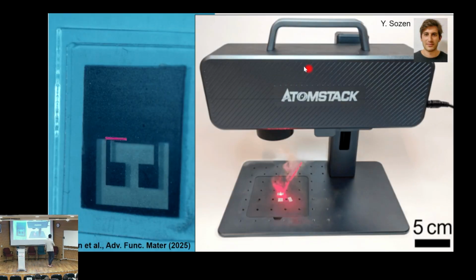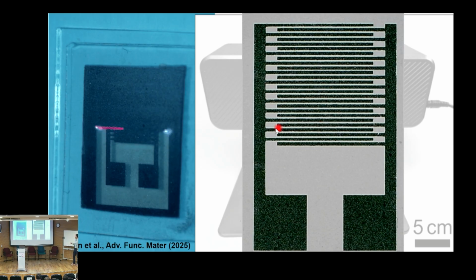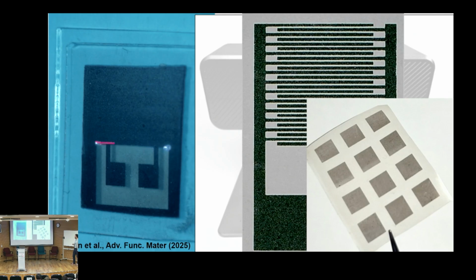When we started to fabricate these kind of batch devices, we got also interested in, okay, now we have these super large area films. How can we exploit the fact that we have large films to make devices even simpler? We happen to have this inexpensive laser engraving machine. Okay, so this is 1,000 euros, something like that, and it works as a charm to do laser ablation of the film. So this is the case of a large area graphite film on polycarbonate, and using this laser, we can ablate the graphite from the regions that we don't want and fabricate, for example, in this case, interdigitated graphite electrodes.